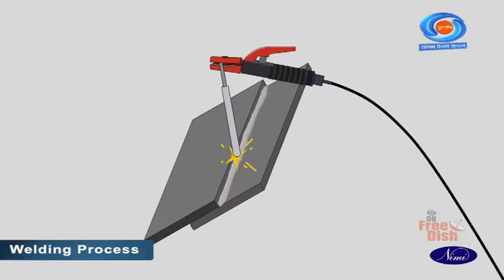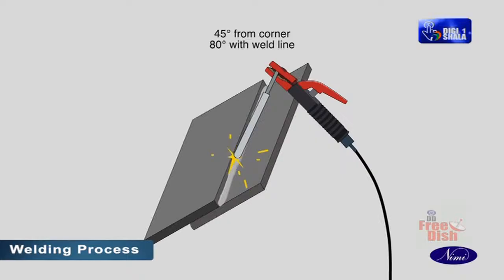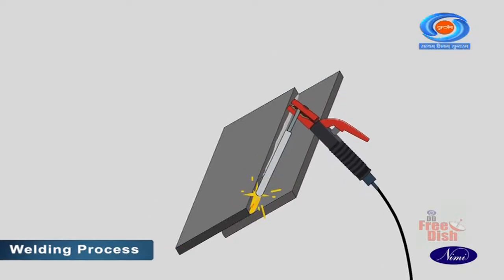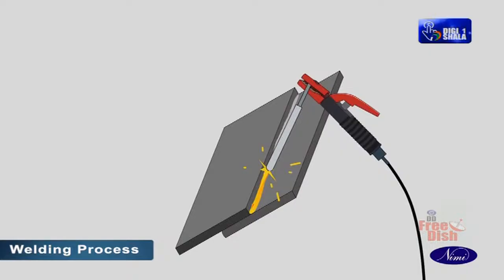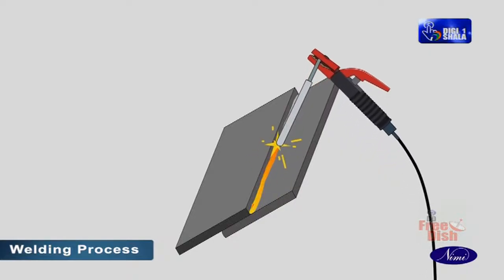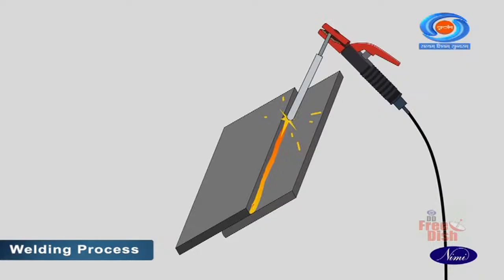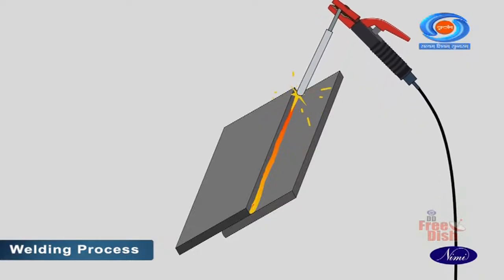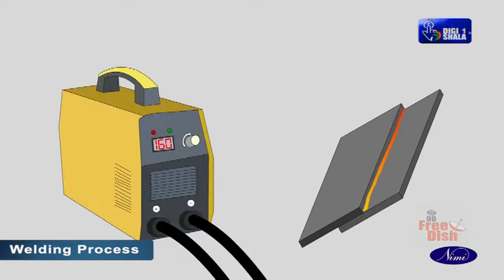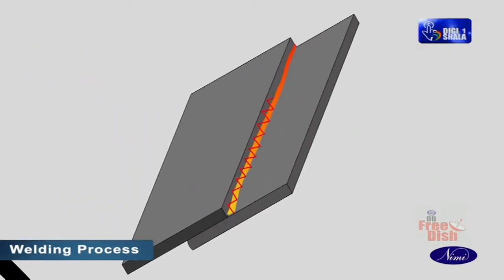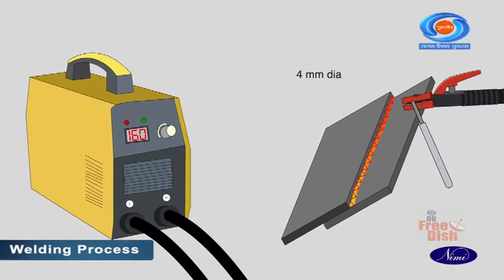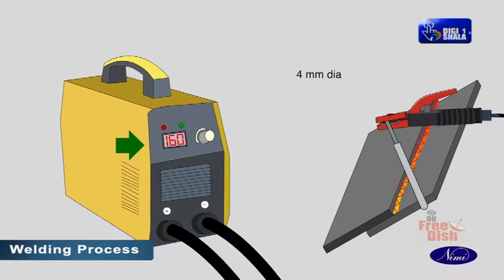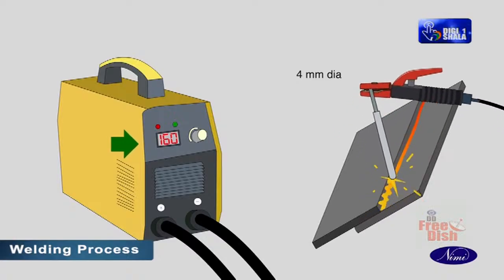Ensure an electrode angle of 45 degrees with the fillet corner and 80 degrees with the welding line. Maintain a short arc to get uniform fusion and root penetration and avoid side-to-side movement of the electrode. Deposit the final covering run with a weave motion using 4 mm dia medium coated MS electrode with 150 to 160 amps welding current.